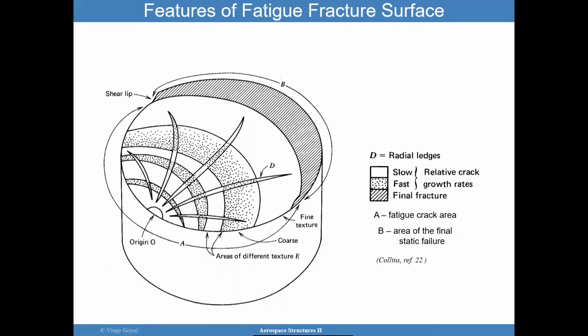Here is an example of the features of a fatigue fracture surface. Here you have the origin, and then you're going to have different areas of texture as you move along, but you can see these marks here. And then suddenly you're going to have some sort of shear lip that could occur, and that's indicative that now you have turned into a sudden failure of some sort.